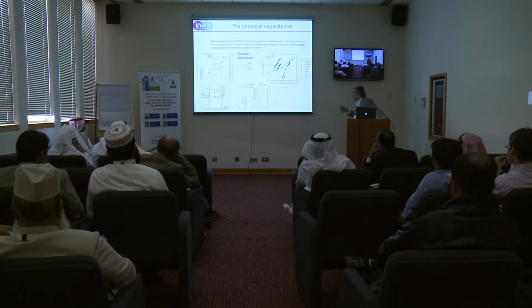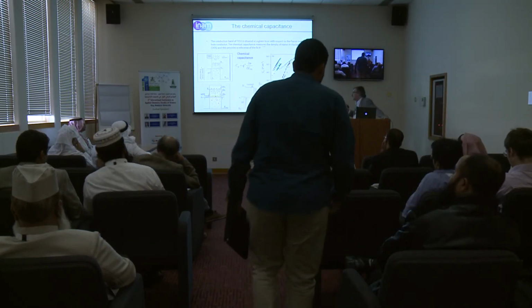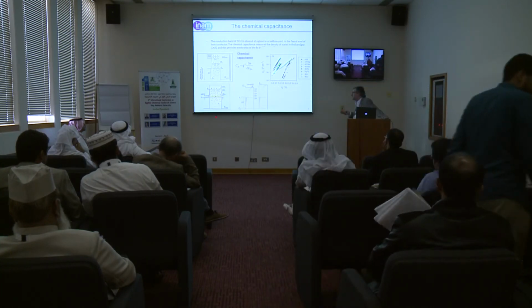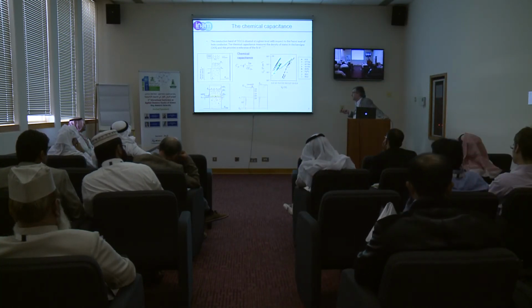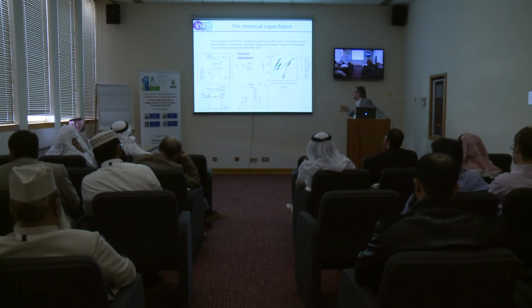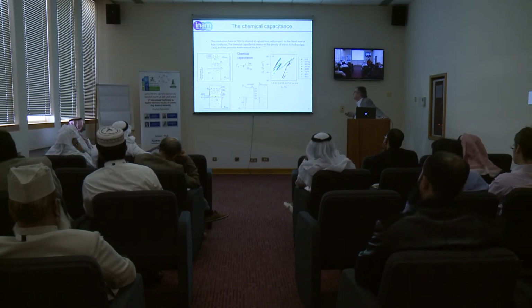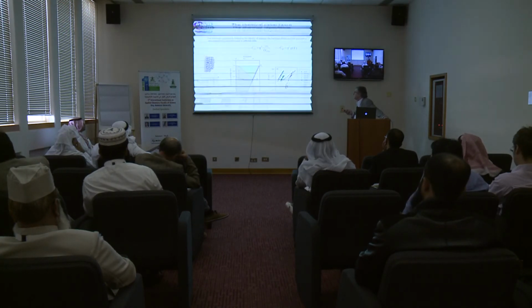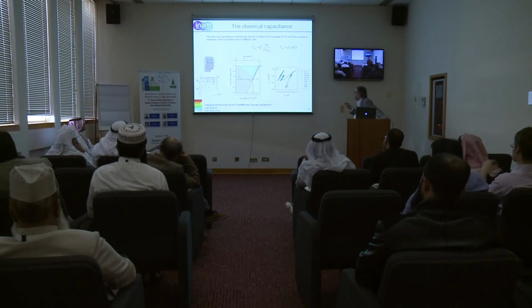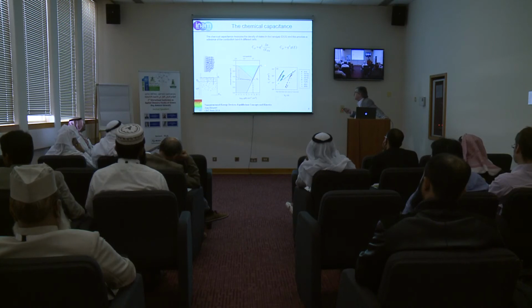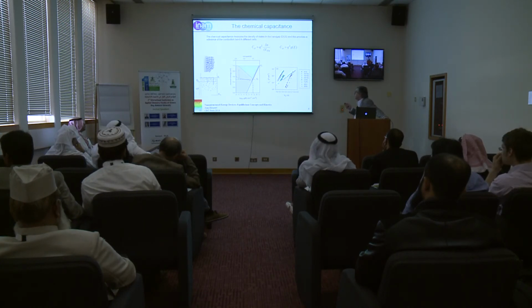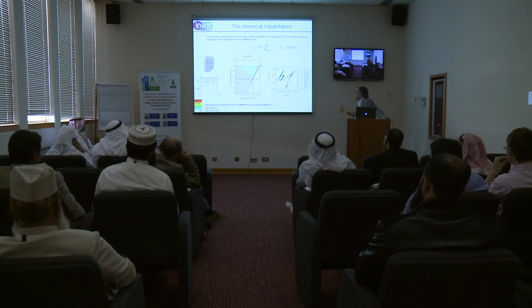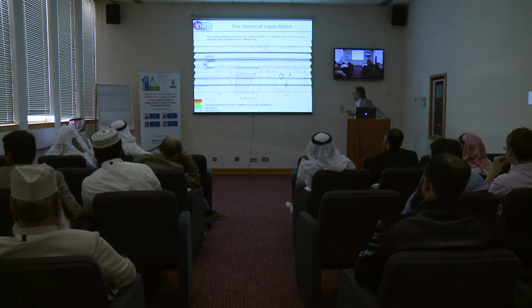So this is called the chemical capacitance because this capacitance arises just from the distribution of electrons in the density of states. And this is something you can measure for any disordered materials. This is related immediately to the density of states, as shown here. So this is a plot of the same concepts. Now you can see here the density of states. We put the Fermi level, and then we get this important formula, which is that the chemical capacitance is really like the density of states.